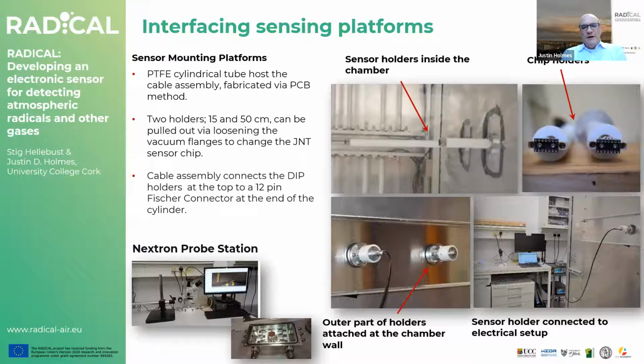So these are the ways that we interface into the chamber. There are these sensor mounting platforms, which are printed circuit boards, and we just attach them into our chip holders, and then we have these rods which go inside the chamber. The cables connect to our electronics, and then we can measure a signal. We also have an Nextron probe station, which is not much used for radicals, but is useful for other gases, where we can flow gases over a chip with electrical probes and measure a change in the conductivity or other parameters within our device. So those are the two setups that we're using at the moment.